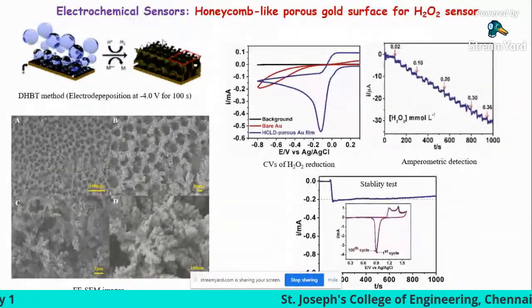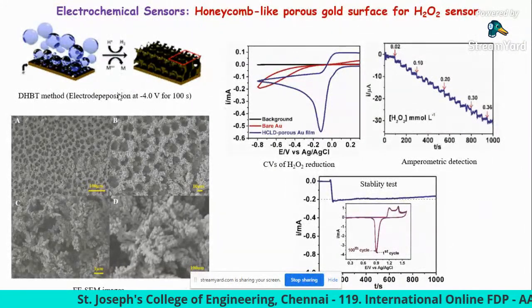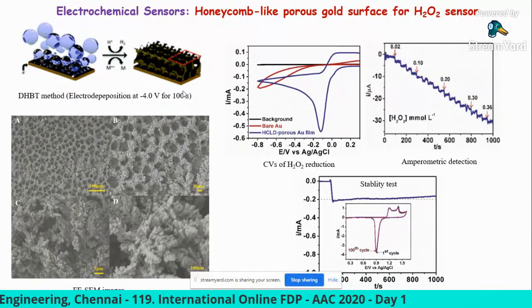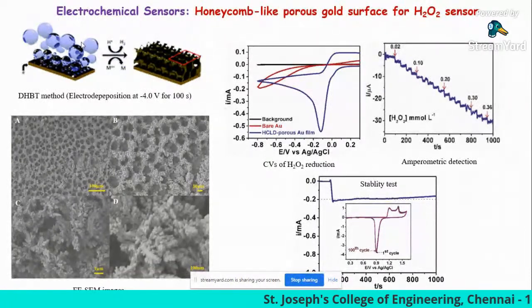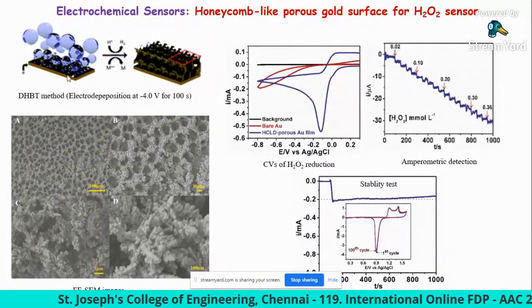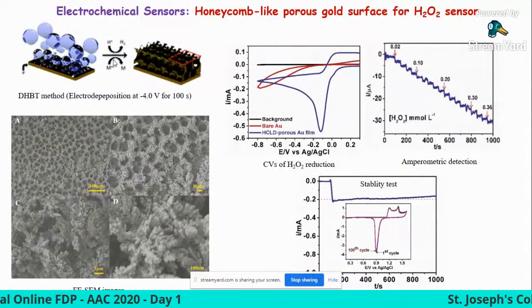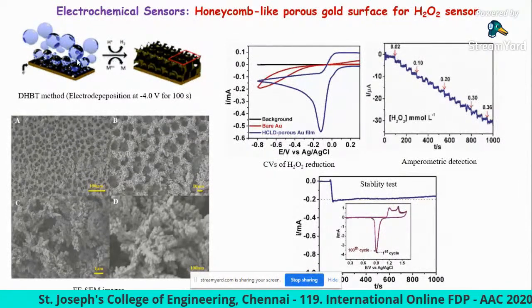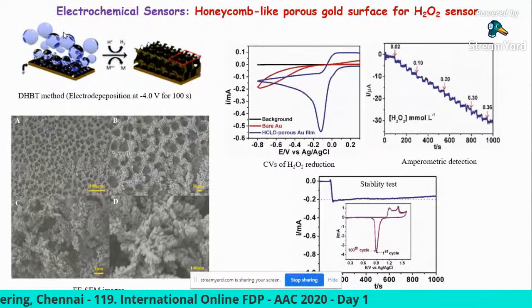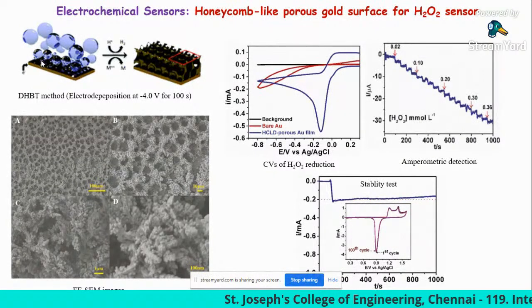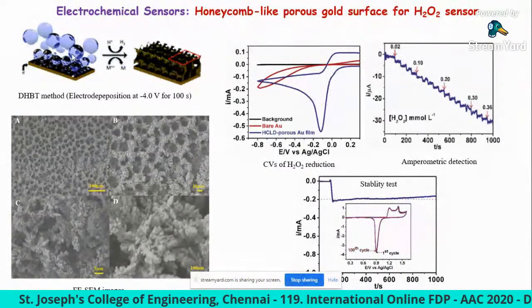If you apply a very high cathodic potential to the gold electrode, say for example -4 volts for 100 seconds, then at this high negative potential, hydrogen bubbles come out from the gold electrode surface. The gold precursor is also there in the electrolytic solution, and at this potential the gold ions diffuse and are deposited over the gold electrode surface. So both processes take place simultaneously. The hydrogen bubbles come out from the electrode surface in one direction, and the gold present in the solution deposits on the gold surface. So this hydrogen bubble can act as a template to form this kind of porous structure.